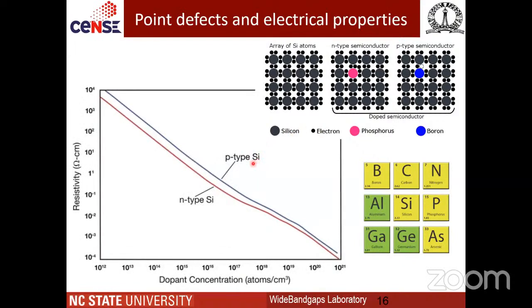Now let's see how the resistivity of the silicon semiconductor changes as you increase the dopant concentration. Let's say that we are in a rather pristine material with only 10 to the 12 dopants. In a 1 centimeter cube volume, typically the number of atoms in the silicon semiconductor would be 10 to the 23 atoms. So when you are doping 10 to the 12 atoms, you are doping it with a rather low concentration. But you soon realize that as you increase the doping concentration, you are changing the resistivity by orders of magnitude. Resistivity is the tendency of the material to resist current conduction in a given unit area. So you see that by incorporating, let's say, 10 to the 17 defects, which is parts per million, you are changing the resistance of the material by 5 orders of magnitude.